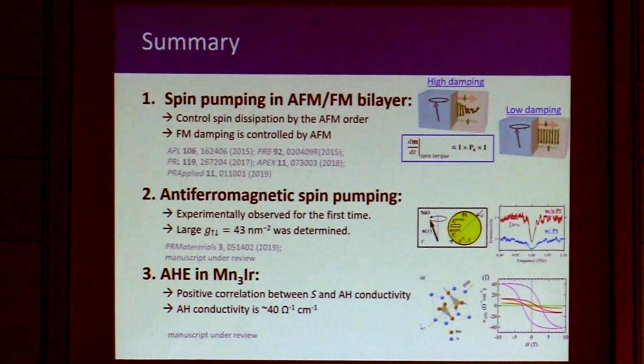Okay, to summarize, first I talked about spin pumping in the antiferromagnet and ferromagnet bilayer, where we can control the ferromagnetic damping by using the antiferromagnetic order. The second one is antiferromagnetic spin pumping, where we can characterize the mixing conductance. And last, we fabricated manganese 3 iridium and saw the positive correlation between the chemical order and the anomalous Hall conductivity.